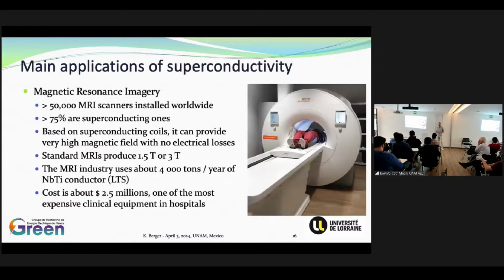The main application right now of superconductors is the MRI, so magnetic resonance imaging. There are more than 50,000 MRIs installed worldwide, and 75% or more of these are superconducting ones. So basically, this is just a coil which you feed with current. When it is a superconducting one, it should be short circuited, so you don't have to feed the current all the time. Since there is no resistance, the current is always flowing in the coil, and it produces a very strong magnetic field. Standard MRIs are in the range of 1.5 or 3 Tesla, but there are new generations above this field. So these are the common MRIs.